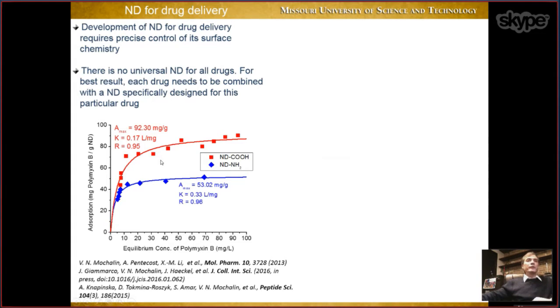For example, I show here the difference in drug loading for two different nanodiamonds. This is aminated nanodiamond, this is carboxylated nanodiamond. And here we use the drug which is called polymyxin B, which is an antibiotic used to kill gram-negative bacteria. And you can see that depending on surface chemistry, the loading, this is simply adsorption isotherms. But this is how you load your drug on nanodiamond, by adsorption. The loading capacity for aminated material is almost twice less compared to carboxylated material.